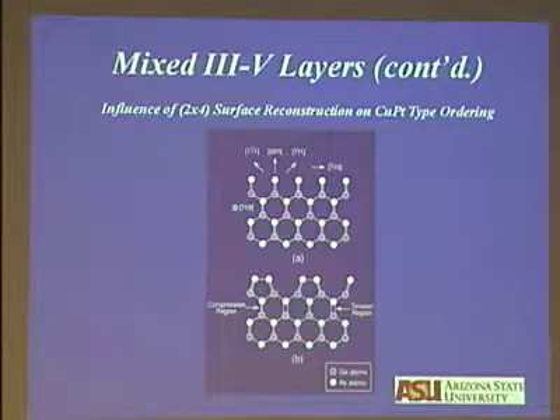Now, indium is a much larger atom than the gallium atom. So what will happen is, the gallium atoms will tend to segregate along this direction, going into the plane. Indium will segregate along this direction. And of course, we don't observe this experimentally, but the net effect is that when you grow the layer, you will produce what is called the copper-platinum order.